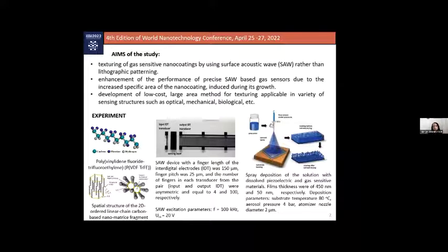The piezoelectric nanocoating, which is necessary to generate the acoustic wave, was polyvinylidene fluoride. And the sensing coating was a carbon-enriched coating, which was previously demonstrated to be sensitive to ethanol. So the two precursors were subsequently grown by spray deposition technique with a fine nozzle of the atomizer and a relatively low substrate temperature of 80 degrees Celsius.